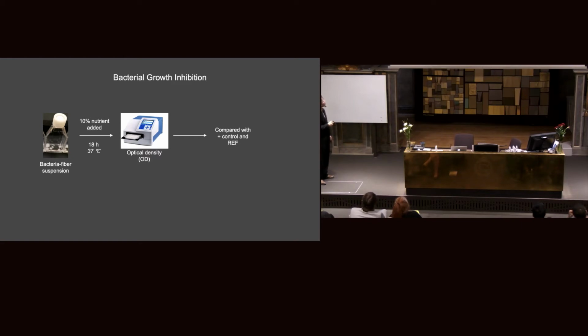Right after the bacterial removal test, we add 10% nutrient to the system. After 18 hours of incubation, we check how much bacteria is left in the solution, and we remove the fibers. We use optical density to see how clear the solution is, and compare that with plus control and references.